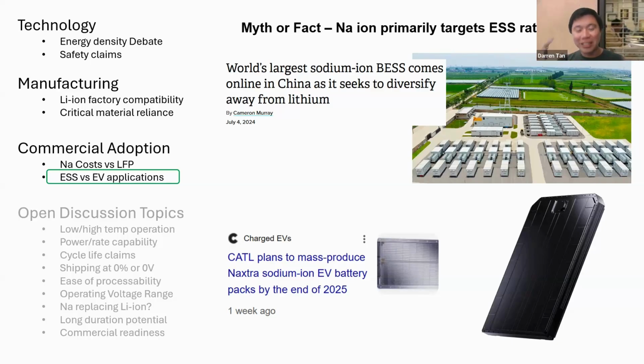Sodium ion is more robust. So when you test sodium ion and LFP at an elevated temperature, for example, at 60 degrees Celsius, you will see LFP crashing really quickly. But sodium ion maintains strong. It's not as good as room temperature, but it still gives you decent thousands of cycles, even at high temperature. Likewise at low temperature too. Calendar life is also pretty good with sodium ion compared to LFP. So I'd say that at the Goldilocks zone, if you keep an air conditioner, thermal management, all your systems are good to go, LFP will win. But if you are deploying it in places where it needs to take a beating, it looks like sodium ion can do a little bit better.